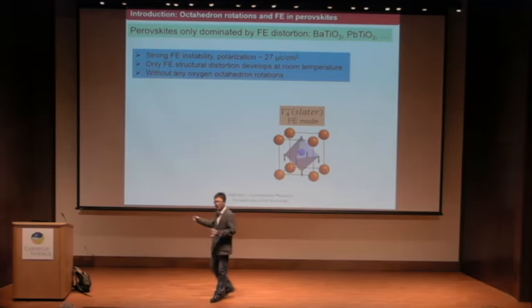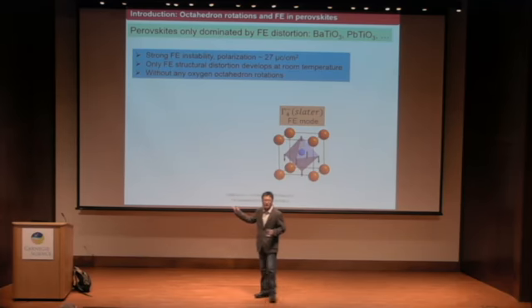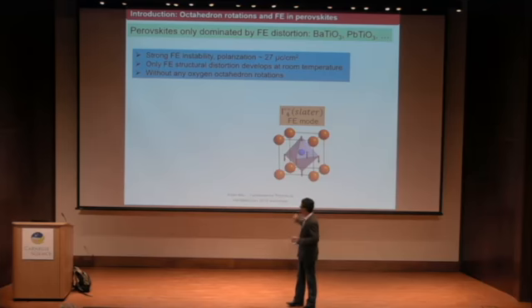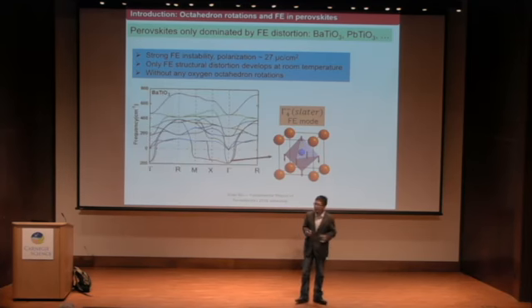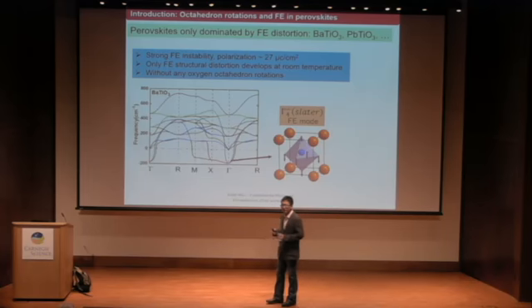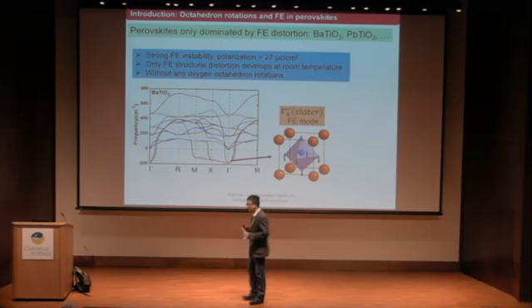Many are functional distortions. For example, barium titanate has this gamma point distortion related to the ferroelectric motion, with cations and anions separating to give a dipole. If you want to understand the origin of the distortion, it's coming from a gamma point instability for cubic barium titanate.